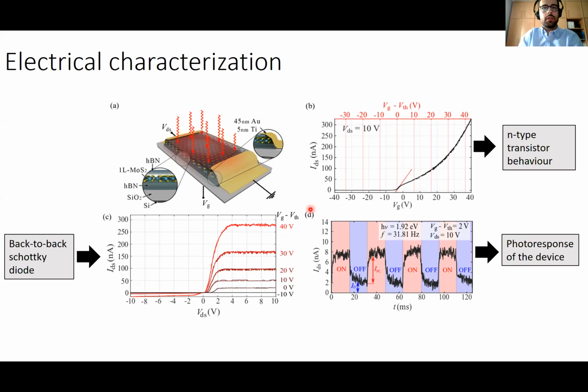When we have done the electrical measurements, we pass to characterize the photoresponse of the device. And here we observe the response of the device as a function of time, in resonance with exciton A, at a frequency of 31.81 Hz. And we observe the on and off regions. And here we have what we call photocurrent. This increase of the current when the light is on over the device is what we call photocurrent. Once we know how the device behaves, we pass to perform the spectral measurements.